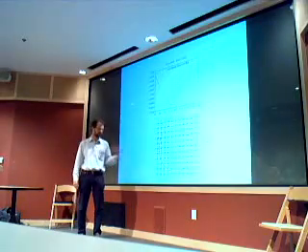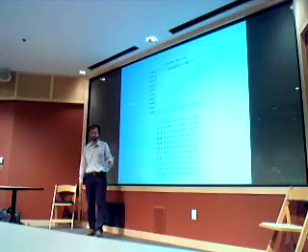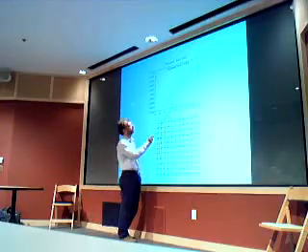Since this is a variational problem, when you increase the variational freedom, the energy will suddenly become better, and this is what happens here. So when new basis functions enter in the calculation, you have sudden drops in the total energy.